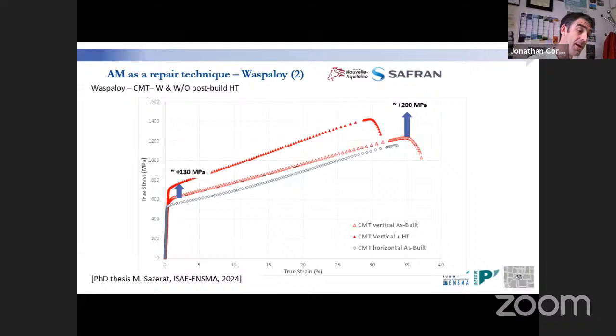But on the other hand, you need to think about improving monotonic properties without degrading the substrate, which is a tricky issue. And we have experiments which will start next week on this with Sandra on the Salsa line, to understand how we can develop heat treatments to both relax stresses and trigger the precipitation to optimize subsequent in-service properties.